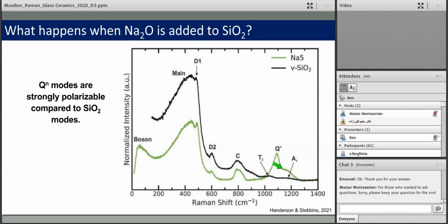Some people would argue that in aluminosilicates and even in silicates, these T2 and A1 modes are found in these sodium-bearing silicate glasses. I would say that something happens here to change the intensity of this band, causing it to become more polarizable and therefore more intense, and that this shoulder at high frequency, extending above 1200 wave numbers, is probably the same as the A1 mode. But as we see no shoulder on the low frequency side, this T2 mode doesn't appear to be present in this band. And of course, if you have sodium influencing the oxygen, you might not get the motion that's associated with this mode. Other people argue that in all cases, at all times, these T2 and A1 modes are there.